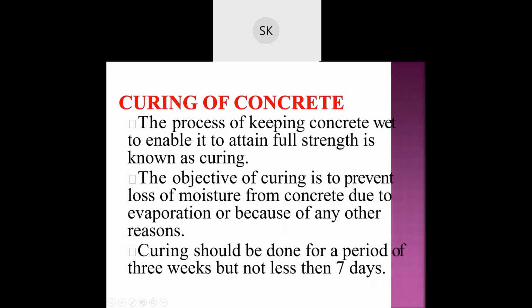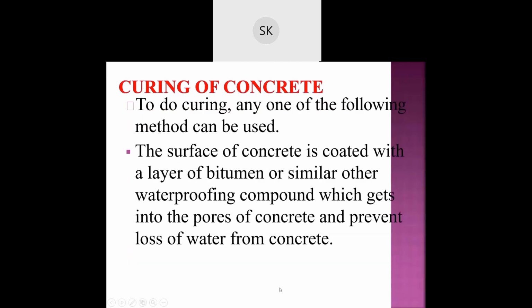Now, the most important is curing of concrete. The process of keeping concrete wet to enable it to attain full strength is known as curing. After casting, you should apply water for 1 to 3 weeks to get its full strength. The objective of curing is to prevent loss of moisture from concrete due to evaporation or any other reasons. It should be done for a period of 3 weeks but not less than 7 days. 3 weeks is better. You can also do 2 weeks, but it should not be less than 7 days.